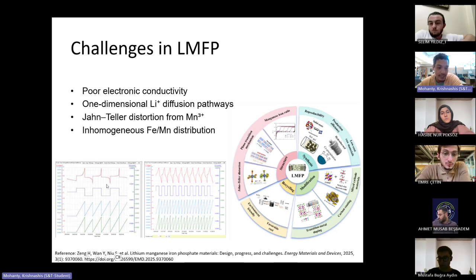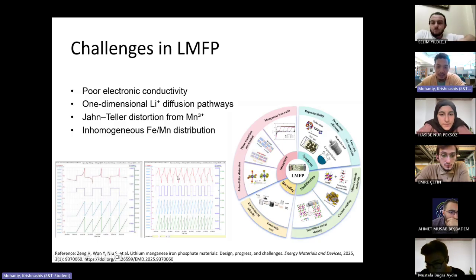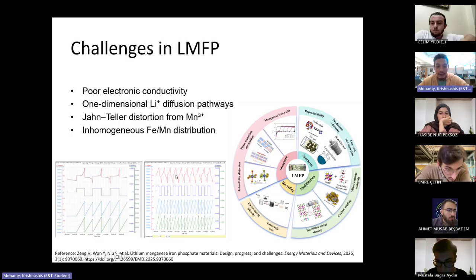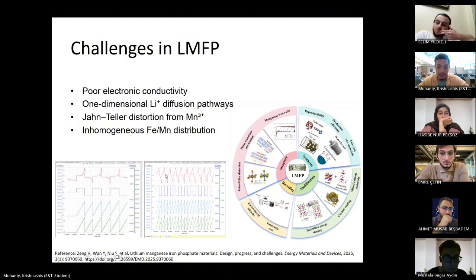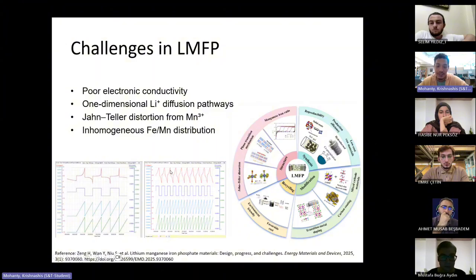And if you compare, on the left hand side, you can see a very distinct and very sharp drop of voltage. But when you see the right hand side, you can see a slope when the charging and discharging happens. And this plays an important role in electrochemistry as well, because if we have a sharp drop in a cycle, it is considered most stable. Because there is a slope here, it shows there is a difference between the iron and the manganese redox reaction. If it was a straight line as in LFP, it would have helped the cycling stability. But as it is not, we have to play around with the ratio of manganese and iron incorporated, which again plays a very huge factor.